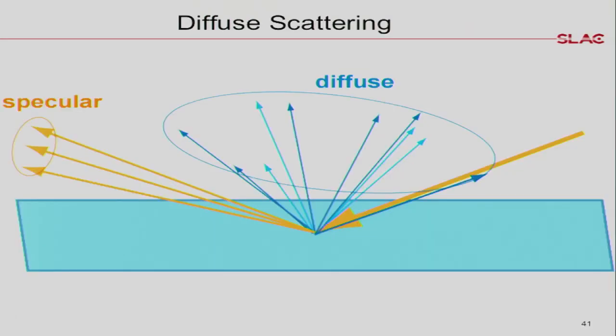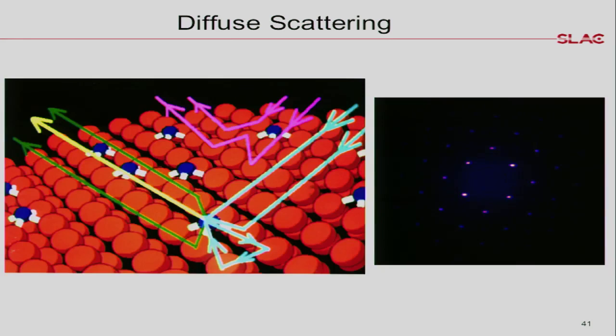The first experiment we look at is diffuse scattering. As you know, when you have a perfect mirror, light comes in and goes out at exactly the same angle. When you have a defect in the mirror, you get so-called diffuse scattering. Most of the time, you say this is bad because diffuse scattering is related to defects in your materials. Same thing with crystal atomic structures. When you have a perfect crystal, electrons come in and you get diffraction, these bright spots called Bragg peaks. But if you have a defect in the crystal, you cause diffuse scattering, which appears between your bright peaks.